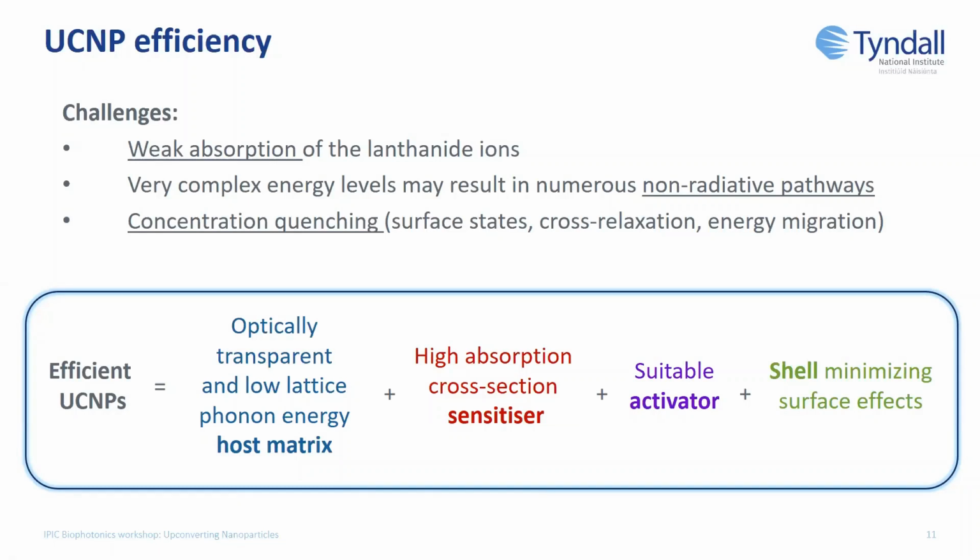And last but not least, we would like to avoid those surface effects, so we can grow a shell around those upconverting nanoparticles, and that will protect our particle from those quenching effects.